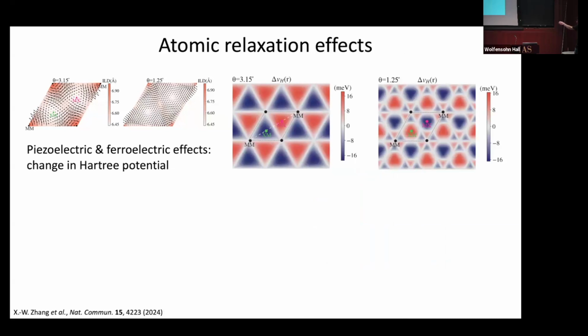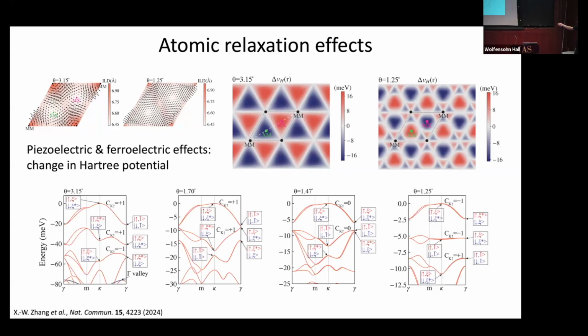by considering piezoelectric effects, basically by considering shifts in plane and comparing effective ferroelectricity and piezoelectricity from polar effects that come from the local arrangements of the metal and chalcogen atoms, they have some calculations where in this regime where we see non-trivial topology, indeed they get the Chern number correct, and indeed the Chern number for the first two Moiré bands for a given value is the same. So this is consistent with what we observe.